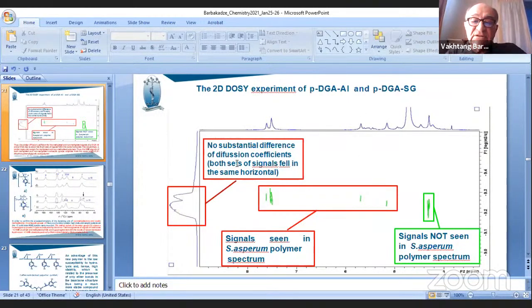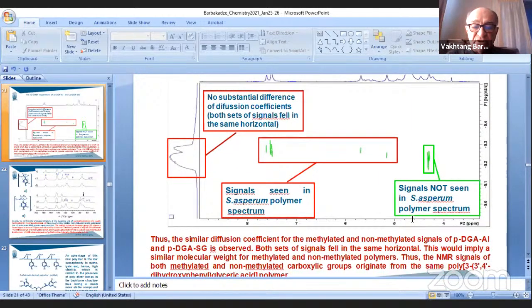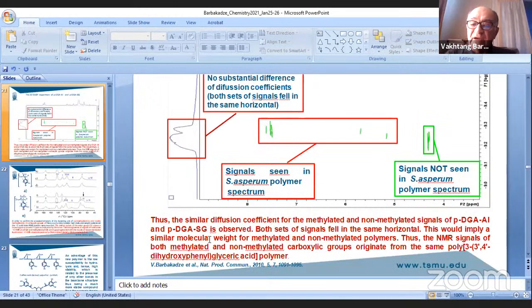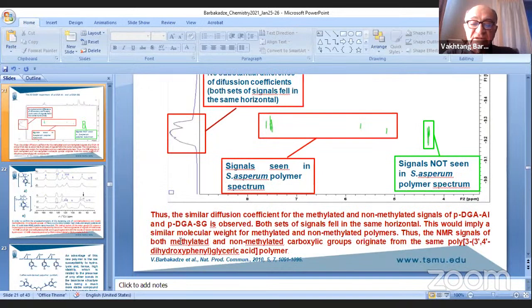No substantial differences of diffusion coefficient. Both sets of the signals fell in the same horizontal. This is a signal in the Symphytum asperum polymer spectrum, and this signal is not seen in the Symphytum asperum polymer spectrum. Thus, a similar diffusion coefficient for the methylated and non-methylated signals of this biopolymer is observed. This would imply a similar molecular weight of methylated and non-methylated polymers. Thus, the NMR signals of both methylated and non-methylated carboxyl groups originate from the same poly-3-(3,4-dihydroxyphenyl)glyceric acid polymer.